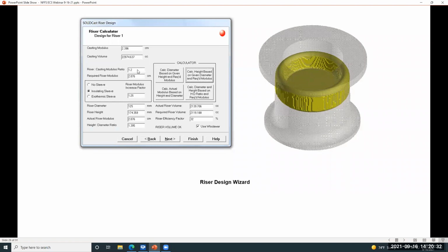Normally, we assume 20% greater modulus for the riser. It also needs to check to make sure that there's enough volume in the riser in order to provide enough feed metal to feed the shrinkage that would occur otherwise in the riser. And this just shows a summary of results here, and it tells us that the riser volume is okay. So we can calculate the diameter of the riser, the height of the riser, and make sure that the modulus information is greater than the casting modulus, and then our volume information is adequate as well.